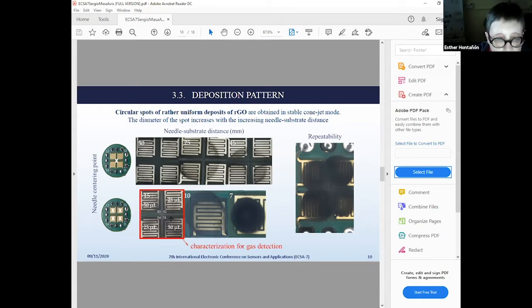You can see also that the surface density of the RGO in the deposits increases when reducing the distance, because of course the size of the spot is smaller, but the amount of material that has been delivered and dispensed is the same. The process is also rather repeatable, as you can see in the image on the right hand side. And we started performing gas measurements with the different sensor substrates.